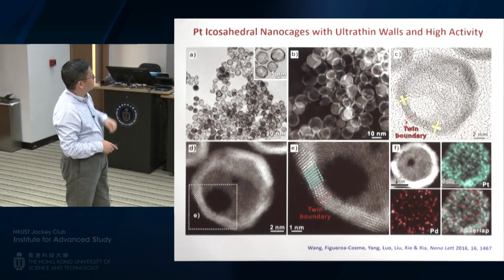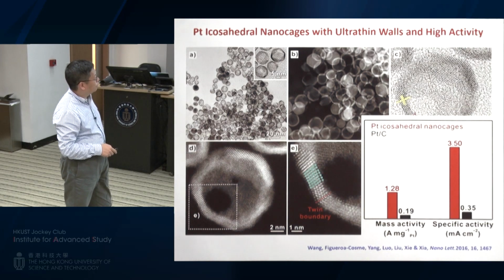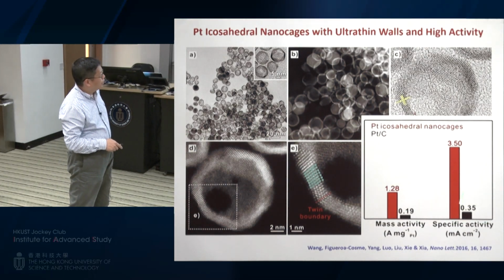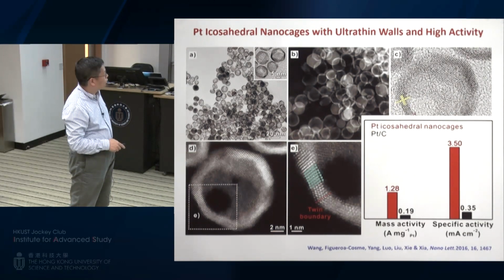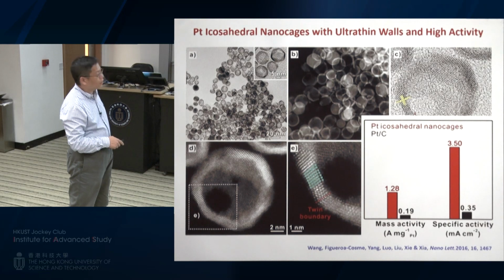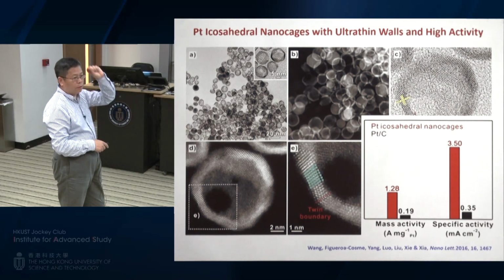And for the initial study, we found that you can observe pretty high specific activity. This is about 3.5. It's as high as the Pt-nickel alloy I showed you earlier. And the mass activity is a little bit lower than the Pt-nickel alloy because in the first demonstration, this shell kept about 6 atomic layers instead of 3. That's something we would like to eventually reach. So that's why the mass activity is only 1.28. If you can reduce to 3 atomic layers, this could be increased to at least 2.0 or even higher.